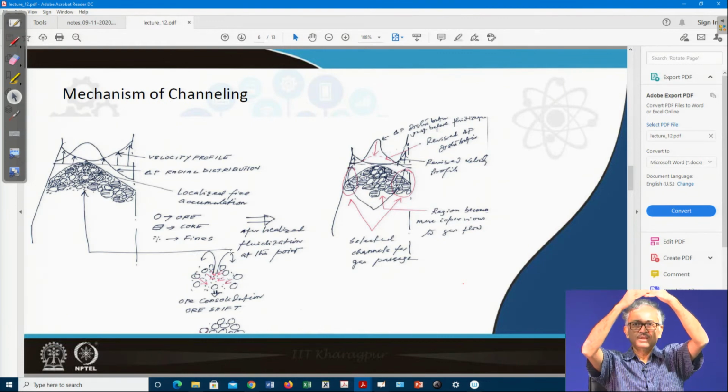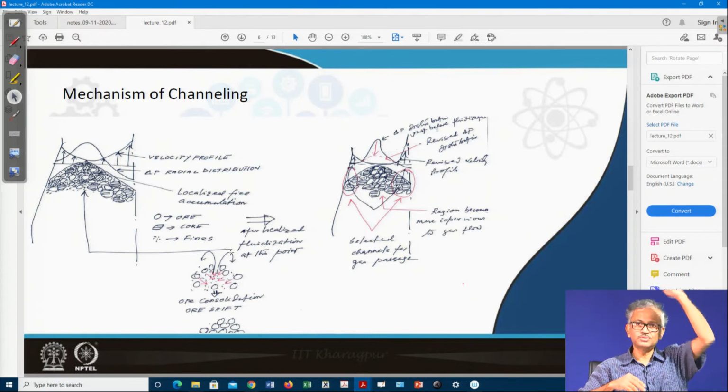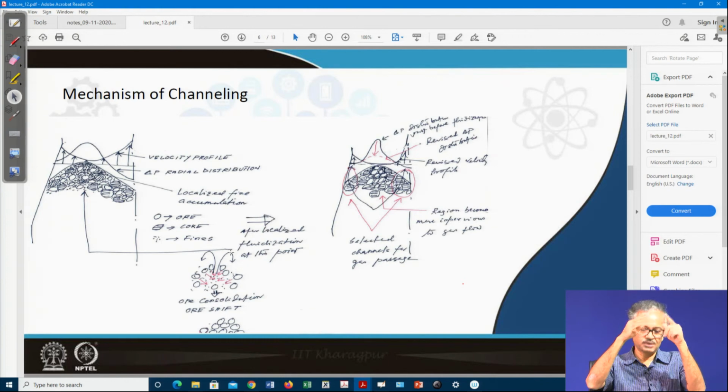It can go up and then again come down, because up there is also a lot of resistance because of all the burdens. So, they will be hit up and then again they will come down. So, these fines, after they get fluidized, again return back and deposit here. And when these fines move up, you can see that between these particles some voids are created, because the fines were sitting there. As they get fluidized, those voids are created.